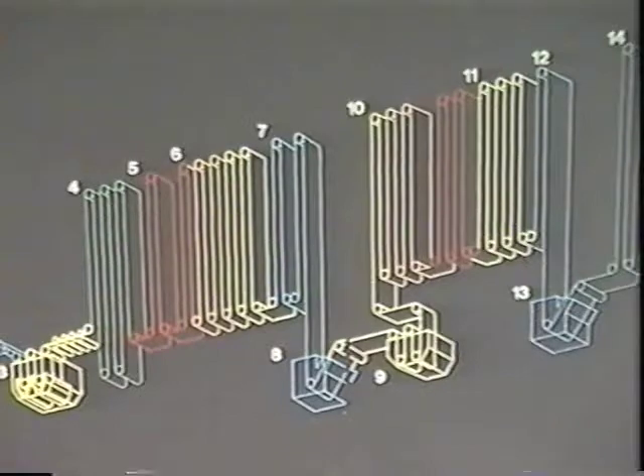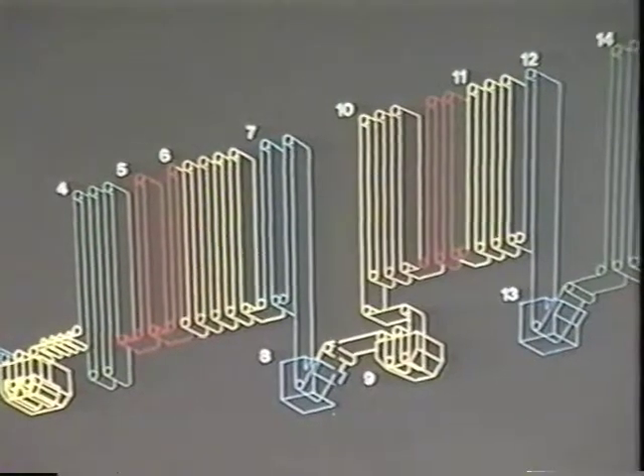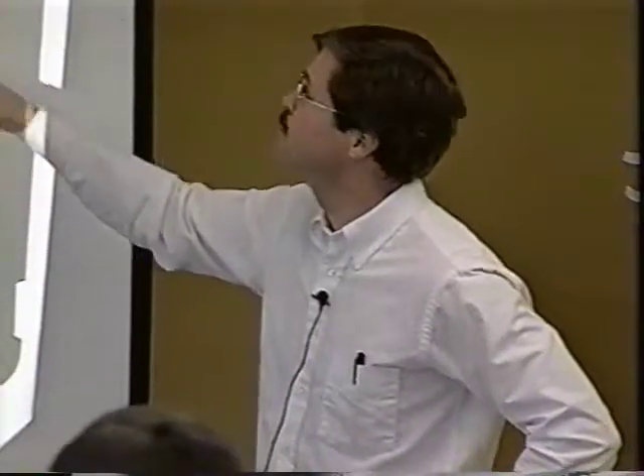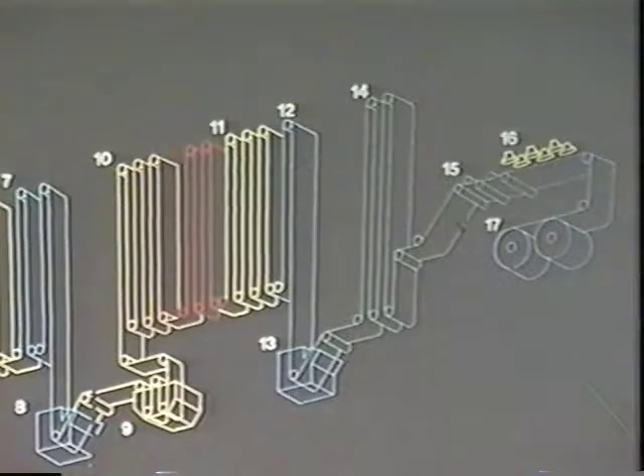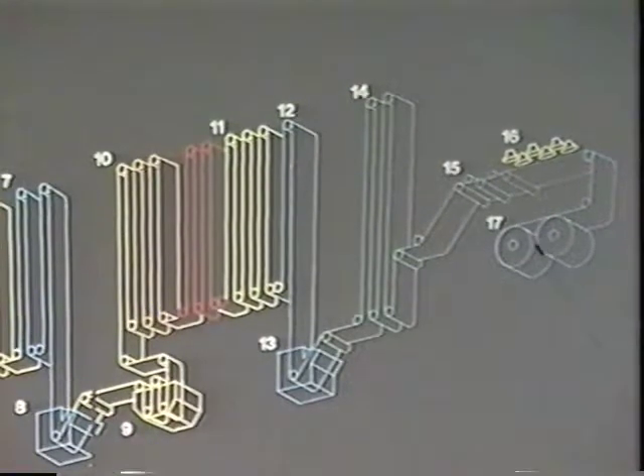If you don't heat it up later on, the carbon is going to move around on itself through time and age the steel. We've heard about aging when we talked about rim steels and old steels in the past, where the steel mill would ship it and it gets harder over time. If we didn't heat it up here, the same thing would happen. Okay? So we've got to heat it up in this overage section, or the steel will age later on and create a thing called strain lines when you go to form it, which is unacceptable. Heat it up to about 700 degrees. Cool it back down. Accumulate it, tension level it, and coil it. Okay?